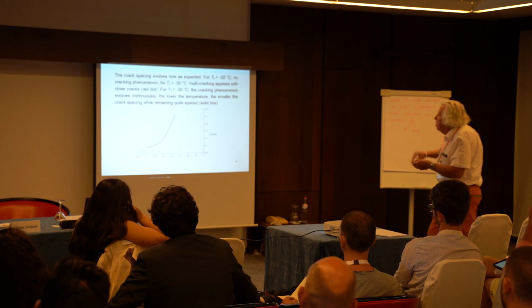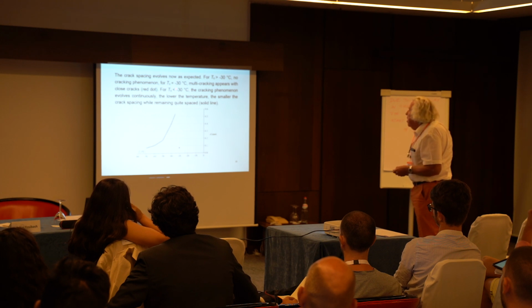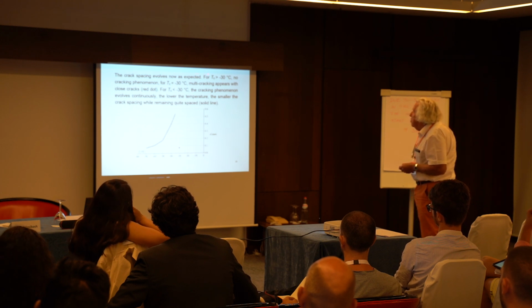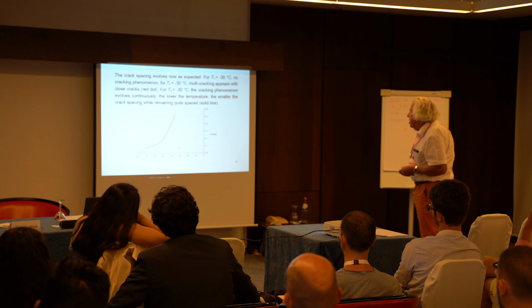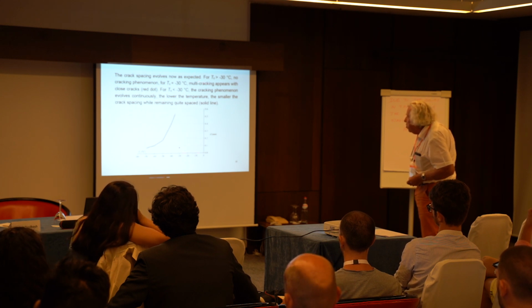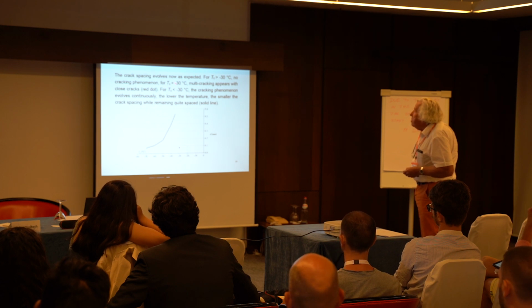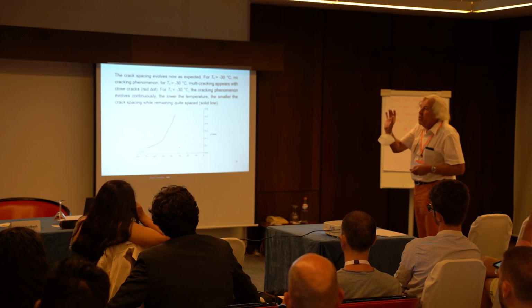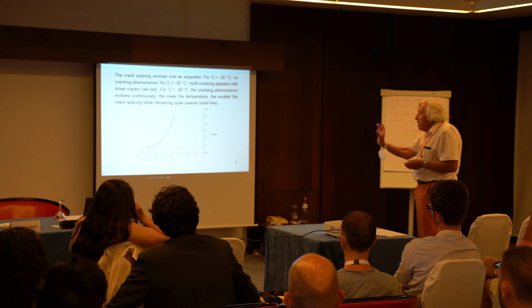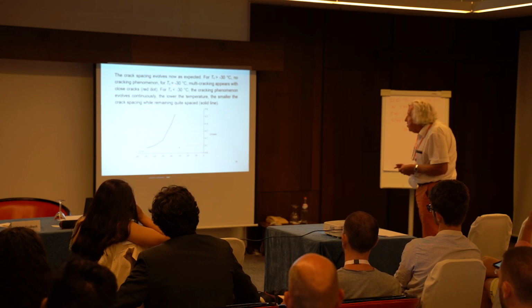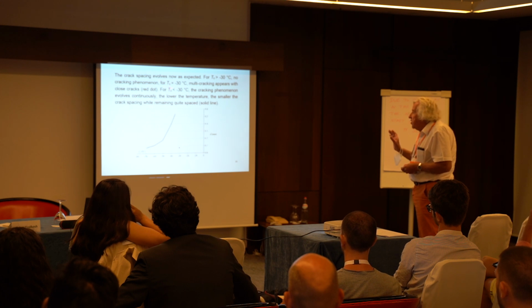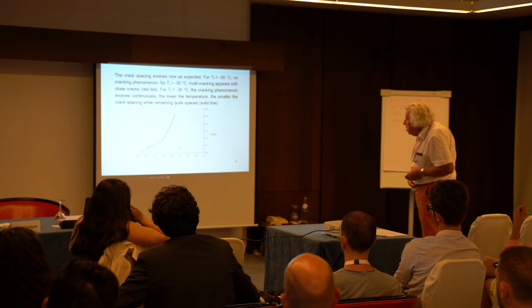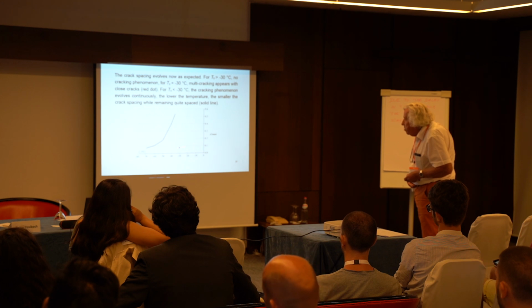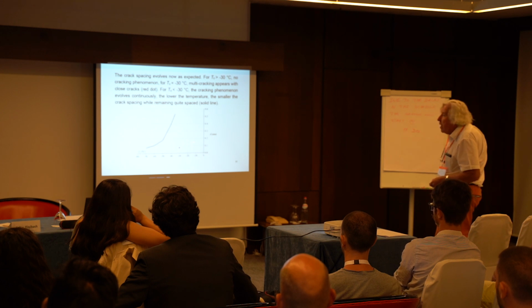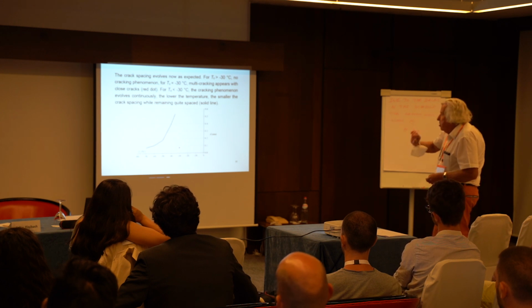And if we go on and calculate for other values, if temperature is larger than minus 20, I mean warmer temperature, there is no crack. At temperature of minus 30 degrees Celsius, it was the hinge, the temperature hinge detected by the experiments. And from this temperature we have derived the value of sigma c, and for this temperature we get that point here. You get a very small distance between cracks, because in our model it's just a simple model.